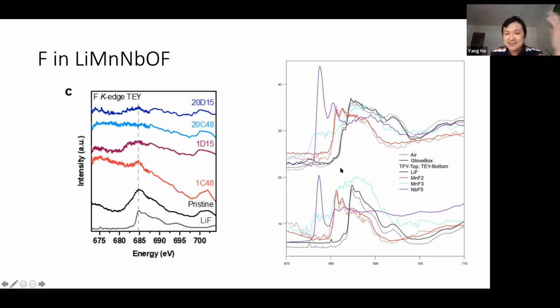So this is just the standard fluoride XAS. In these battery materials, we measure the transition metal fluorides, like niobium fluoride and manganese fluoride, to see what a transition metal fluoride covalent bond looks like. And we also measure lithium fluoride, indicating an ionic bond. And when we measure our real electrode, we see that it's mainly ionic interactions, meaning the fluoride has a weak interaction with the transition metal ions.